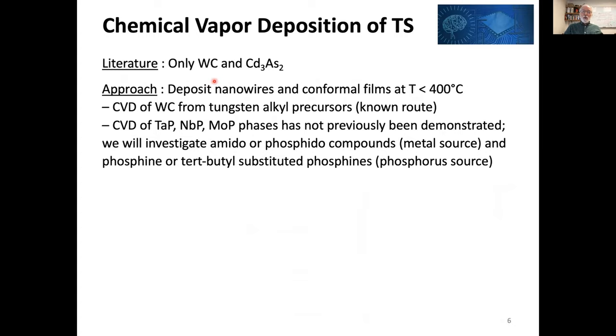Now, what specifically can be done by this technique? We have only seen references to tungsten carbide and cadmium arsenide. What we want to do is to deposit nanowires and films, including conformal films, at temperatures within a practical thermal budget. By the way, much less than 400 is really the target. We're going to start with something that is known, tungsten carbide. We're going to use tungsten alkyl precursors. So start with something we are confident we can do. We're going to branch out to CVD of these phosphide phases. By the way, two of these are Weyl semi-metals and two are unconventional semi-metals. So we have here some bandwidth in the physics of what we're looking at. And we have an initial well-considered choice, amido or phosphido compounds for the metal source, phosphine or tert-butyl substituted phosphines as the phosphorus source.